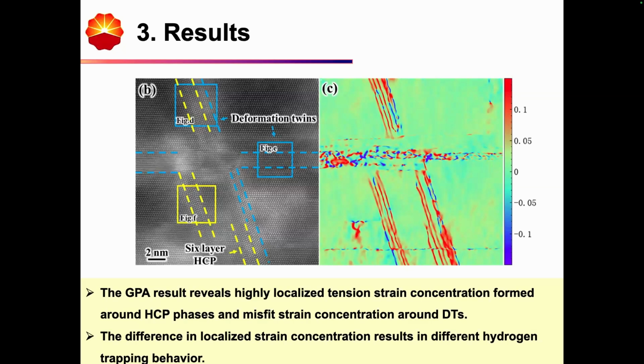After that, we discuss that because we have formed such complicated microstructures, and we know that both the HCP phase and the deformation twins are important hydrogen trapping sites, the hydrogen trapping behavior is different because of the localized strain concentrations.